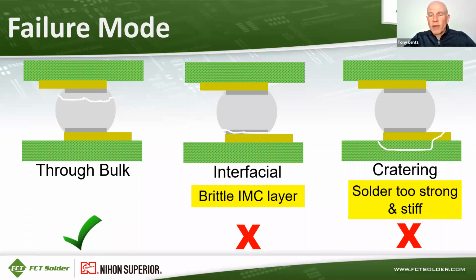Pad cratering also might indicate that your solder alloy was too strong and too stiff and didn't comply or move with thermal cycling, and the materials around it were the weak spot. And so if the pad rips out of the circuit board, of course, that's not a repairable defect.